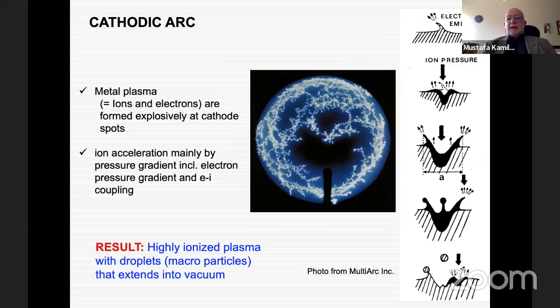In the meantime, there's also another issue that takes place. This is droplet formation. When this metal melts, there are small metal pools that form on the cathode surface. They may spit out particles in micron size onto the substrate surface. So this is one of the drawbacks of cathodic arc technology, this droplet formation, but it doesn't create a big deal mainly for hard coating applications.